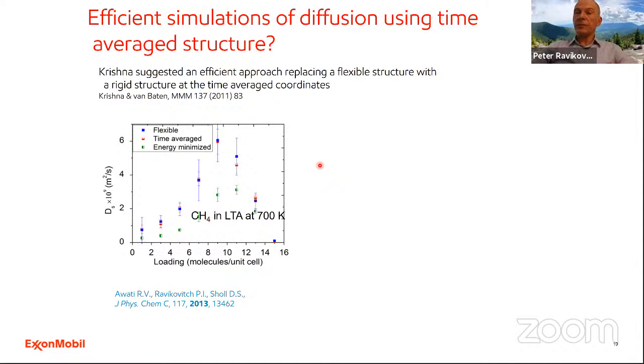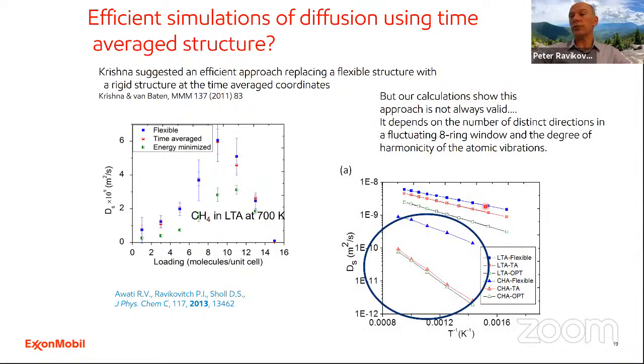How can we do this? So in the literature, there was a suggestion that flexibility can be taken into account by performing simulations with the flexible structure and then taking some sort of average. And it works for some of the structures, such as, for example, LTA, but it doesn't work for other structures, like chabazite. And the problem here is it really depends on the number of directions in this fluctuating window, and also on the degree of harmonicity of atomic vibrations.